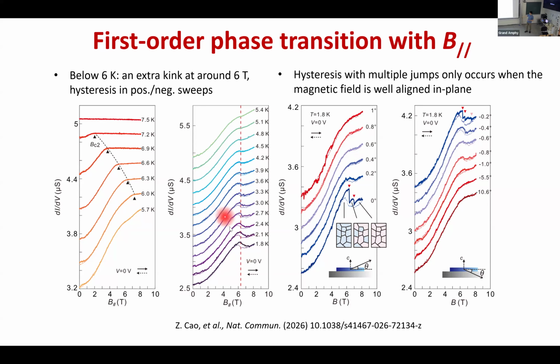Also, this is not perfectly aligned to the in-plane. If we really apply the field in-plane, we see that there are really some jumps around this transition point, and this is very sensitive to the in-plane field. If we tilt it just about 0.1 or 0.2 degrees, then it's not very clear. Within 1 degree, it disappears. So you don't think flux lines could explain the jumps? The flux lines cannot explain why it happens exactly at this field.